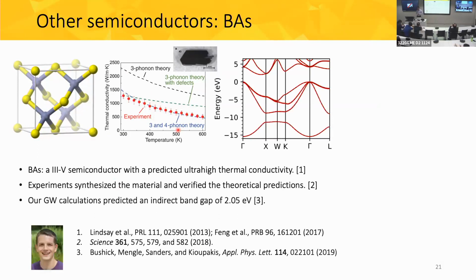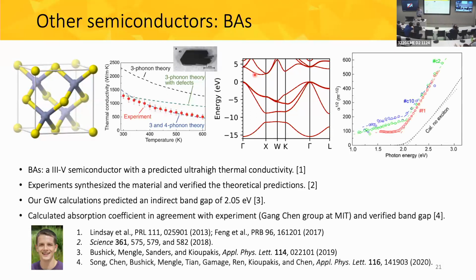So what we did at the time is we investigated with GW calculations to find its band gap and found that its band structure looks a lot like silicon, except its indirect band gap is about 2 eV. So that was the prediction for the magnitude, but the material has just been made. So at the time, there were no measurements of the band gap itself. And so that's when we collaborated with the experimental group of Gang Chen at MIT, who did the optical measurements and found that indeed the calculated coefficients and the band gap agree very well with experiments and verified indeed that the band gap is indeed 2 eV.